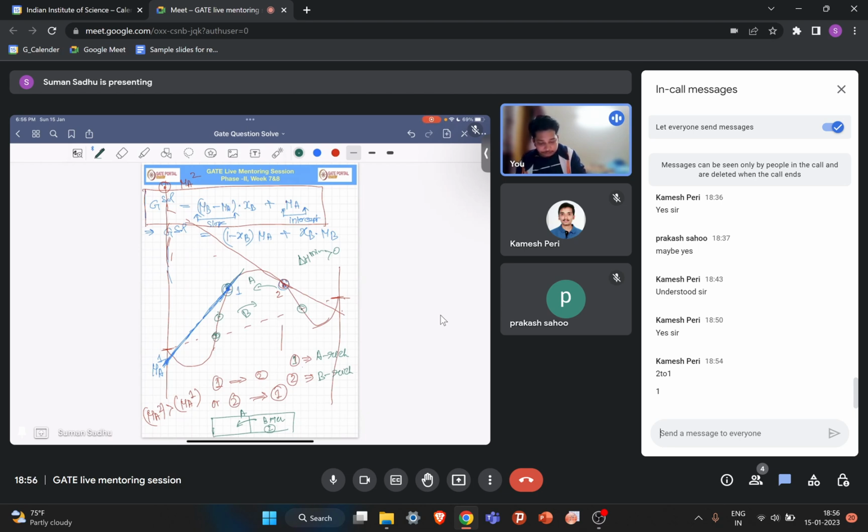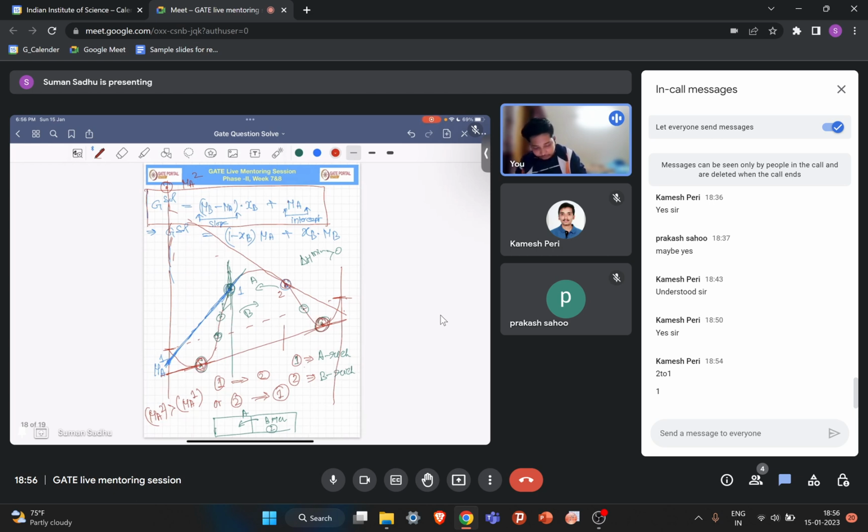So if you have this composition in your phase diagram, it will automatically move in this direction and split into these two compositions, because it will minimize your free energy. This process will continue until you get the same chemical potential. If you draw a tangent covering this point and this point, you will get a common tangent for these two points. So what is the meaning of a common tangent? A common tangent means this phase and this phase will be at equilibrium because mu a is equal. So let me draw it here, otherwise it is looking very bad.